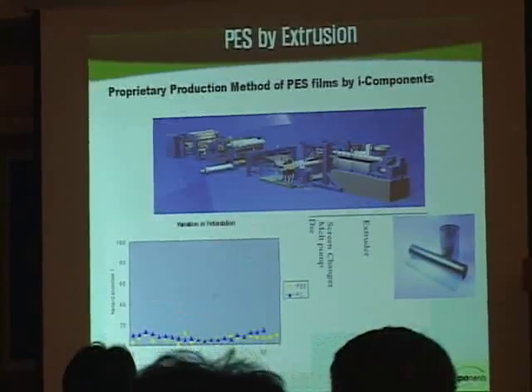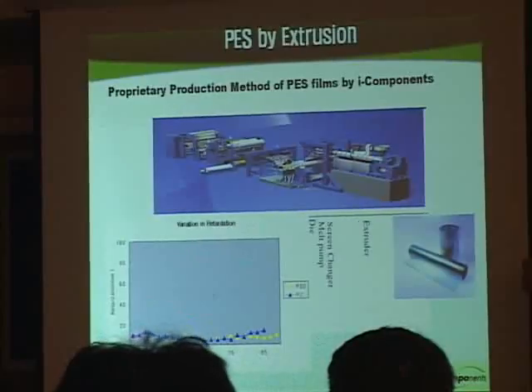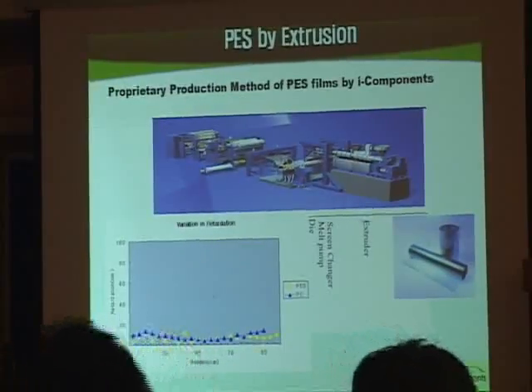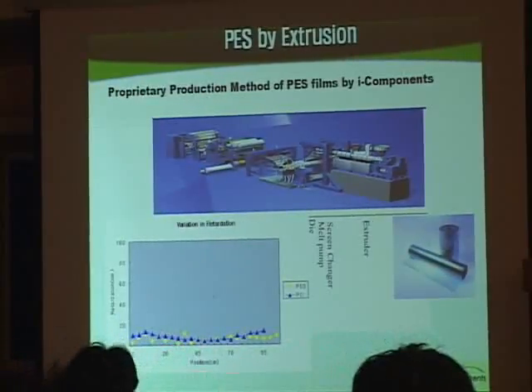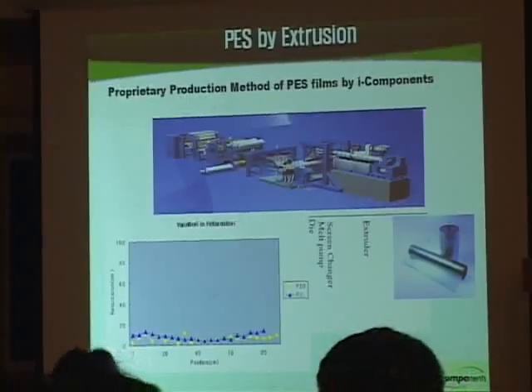Variation in the retardation is around 10 nanometers. As you see here, this is 1 meter width. When we extrude our film, we make about 1.2 meter width. And out of 1.2, we check 1 meter width, and optical retardation is pretty good. So the PES film, we developed this already to be used in the LCD.